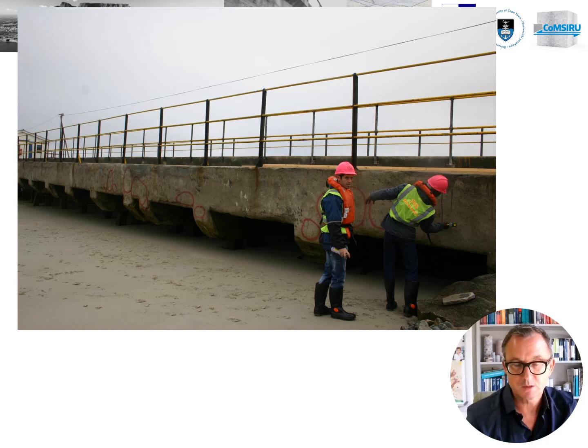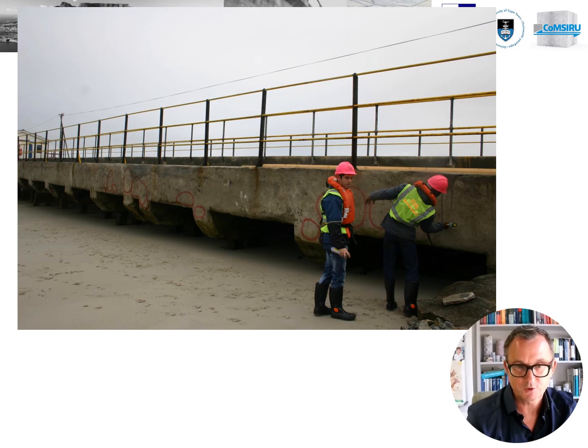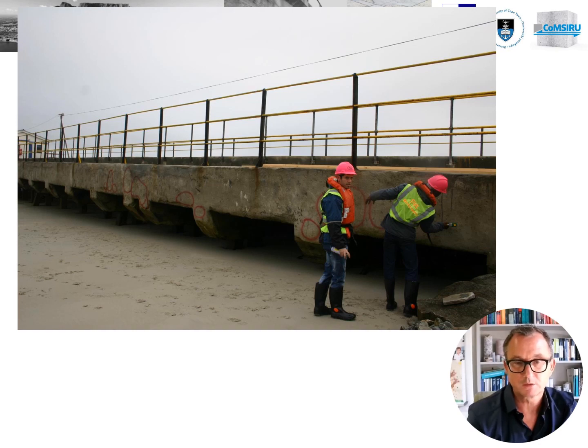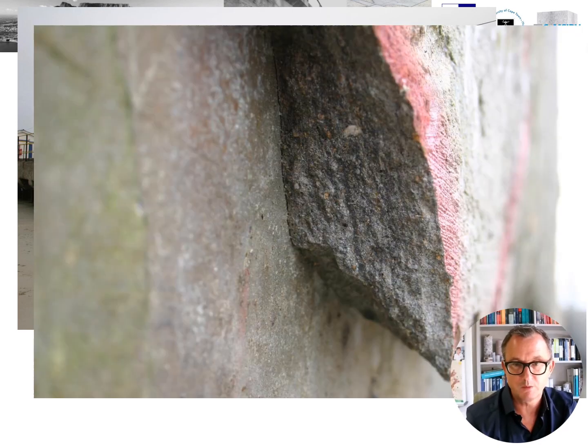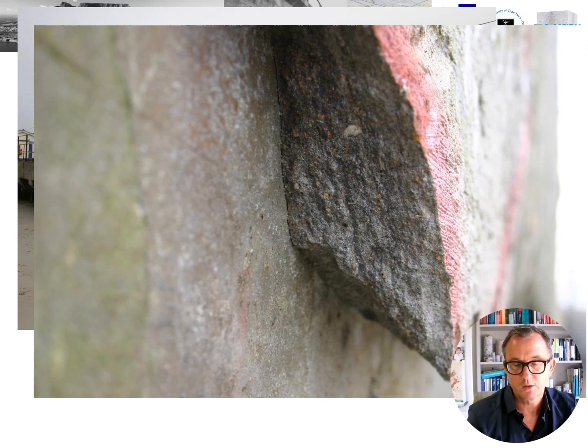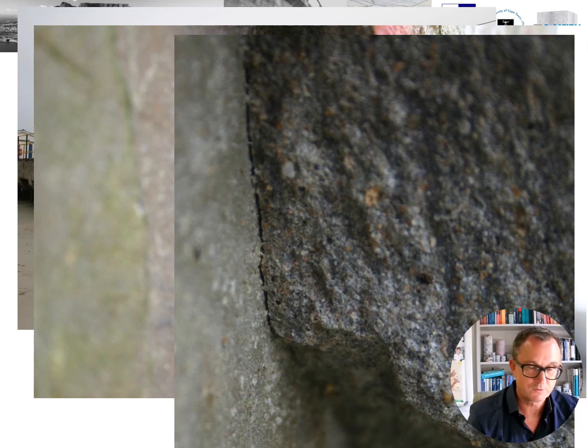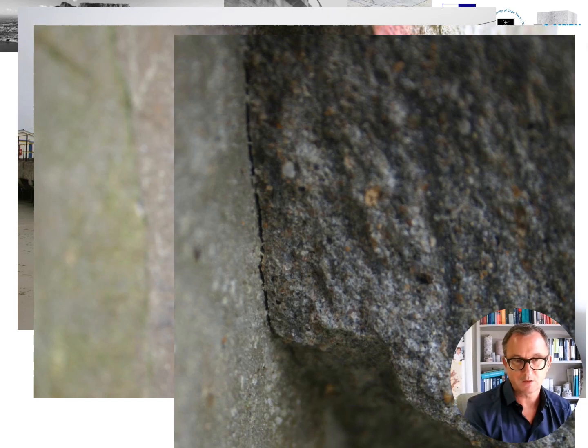Here we investigated a jetty on the west coast in South Africa where a large-scale shotcrete repair had been applied which was debonding. When we looked at this in more detail, you could see the shotcrete was very dense, high quality, good material — but applied to a smooth, unprepared concrete substrate surface. On smooth unprepared surfaces it is very difficult to achieve bond even with very good materials, so surface preparation clearly is very important.